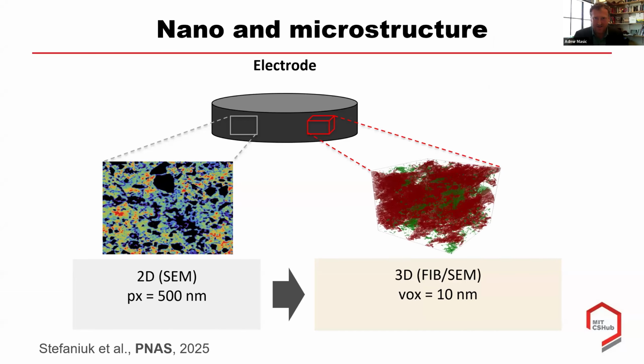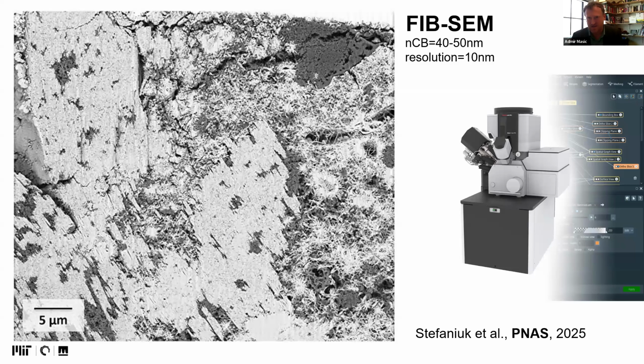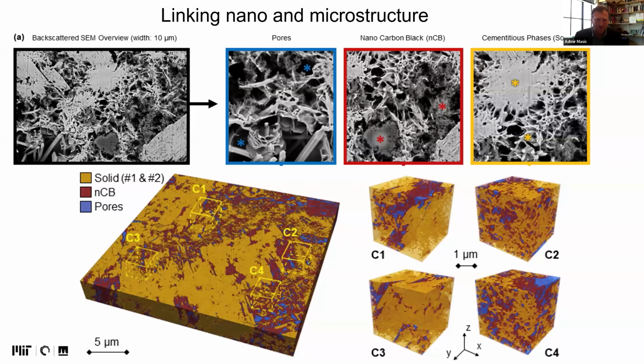Recently, we investigated closely the micro and nanostructure of this composite using different electron microscopy tools, including this FIB-SEM tool that has a resolution of 10 nanometers, where our nanocarbon black generally is 40, 50 nanometers. And using this tool, we were able to really resolve the distribution of different components, including solid hydration products, yellow in this 3D reconstruction, red is nanocarbon black, and pores.